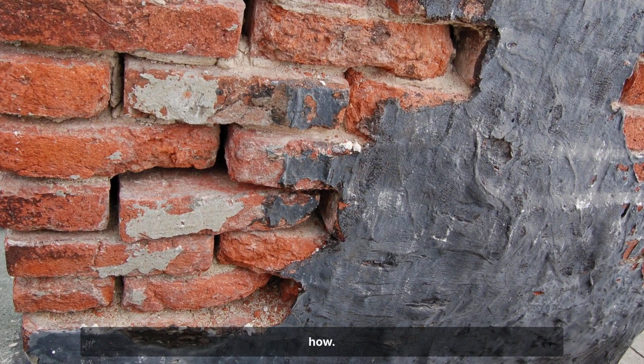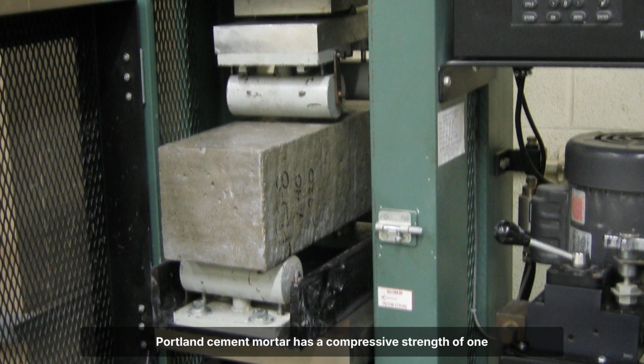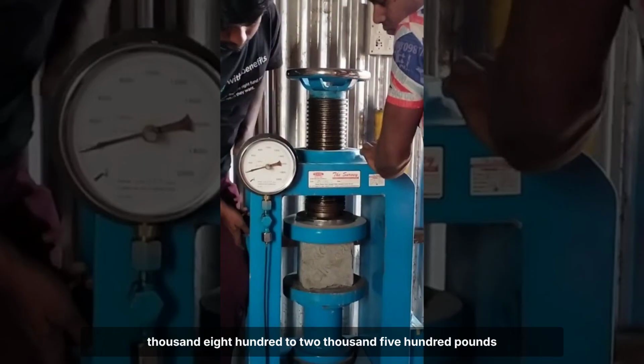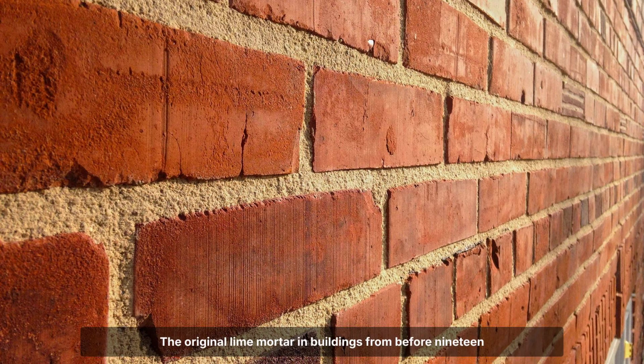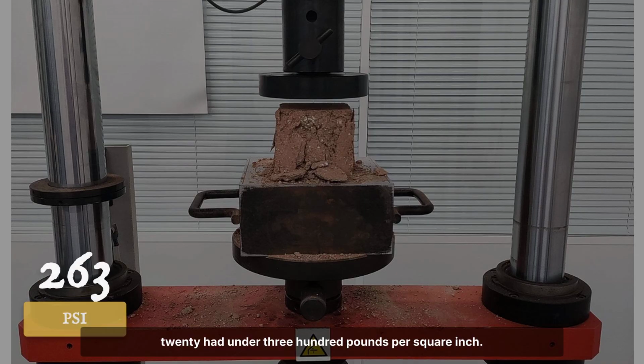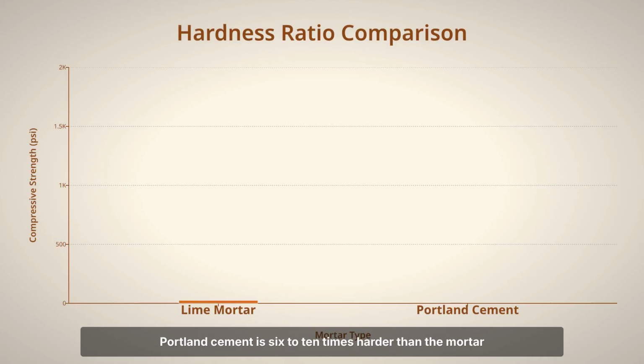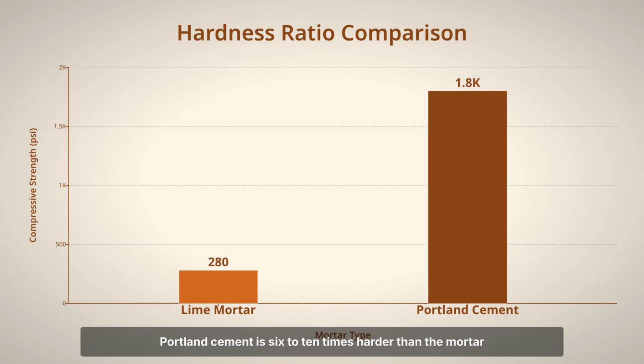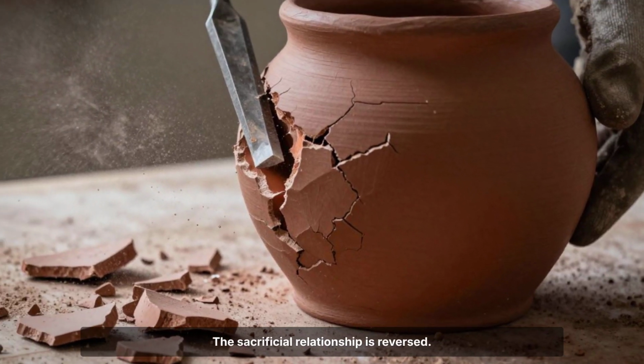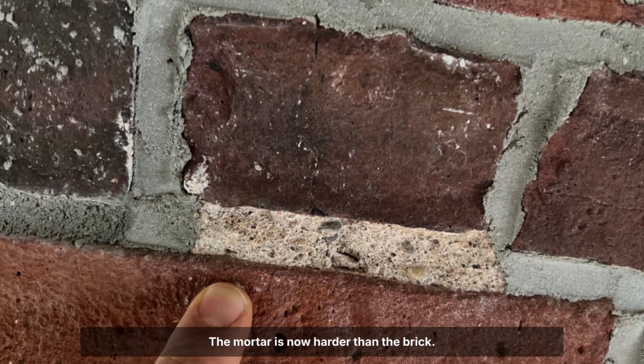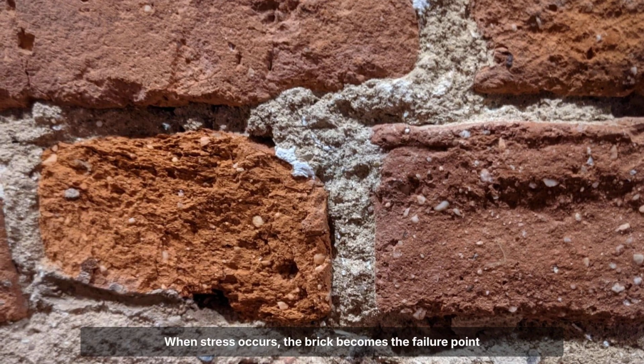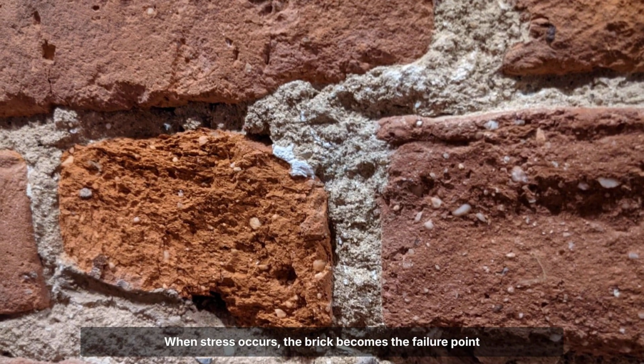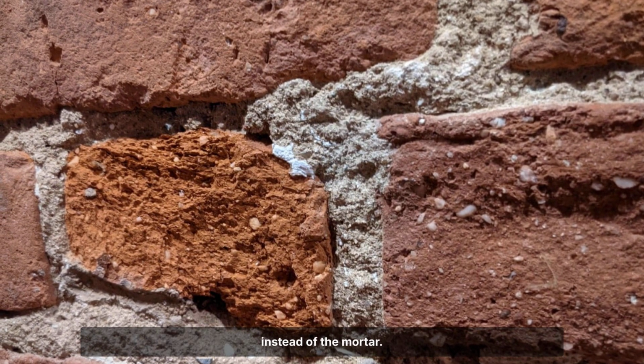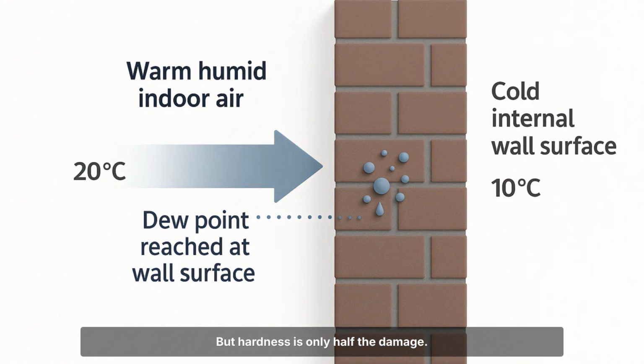Here is exactly how. Portland cement mortar has a compressive strength of 1,800 to 2,500 pounds per square inch. The original lime mortar in buildings from before 1920 had under 300 pounds per square inch. Portland cement is 6 to 10 times harder than the mortar it replaces. The sacrificial relationship is reversed. The mortar is now harder than the brick. When stress occurs, the brick becomes the failure point instead of the mortar. But hardness is only half the damage.